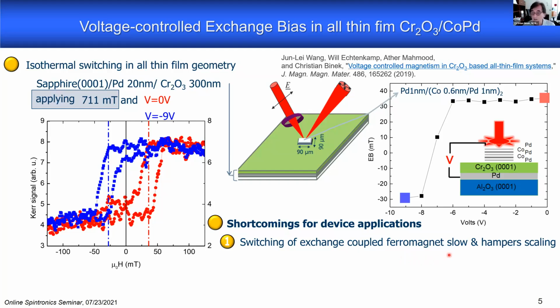And in addition, and I don't go into the details, but by now there are actually multiple manuscripts that discuss this in more detail. If you start to scale down your system, roughly speaking, if you reduce volume from the antiferromagnet, you find that the interface interaction starts to play more and more of an important role. And that breaks a symmetry in this whole system, in the sense that switching in one direction, guess what? The direction I show you here is easier than switching, far easier than switching back. In one direction, so to say, the exchange interaction supports that switching.